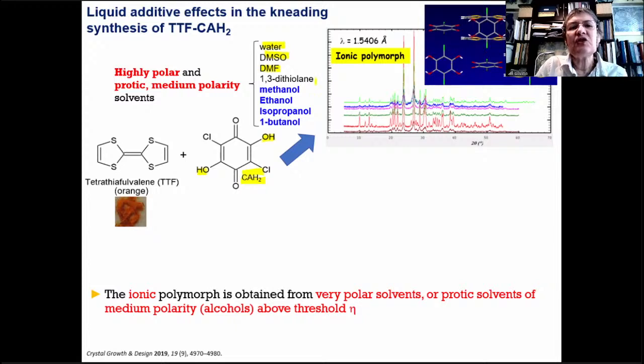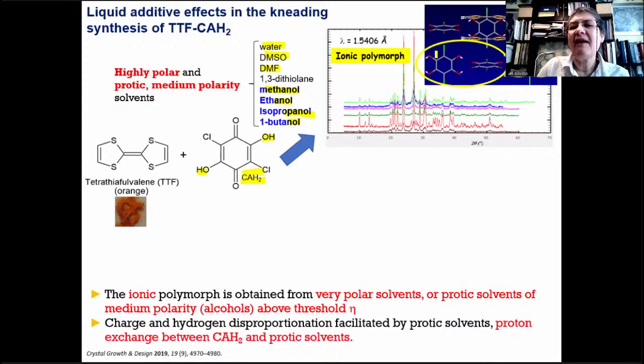And an interesting issue is that solvents of medium polarity, such as these alcohols, methanol, ethanol, isopropanol, and 1-butanol, also produce this ionic form. And these liquids always have to be used above certain threshold amounts to obtain single phases of this material. So in the ionic polymorph, we have a charge and hydrogen disproportionation occurring, in which between two chloranilic acid molecules, one of them has all the hydrogens, these 4 hydrogen atoms there, and the other one has all the charge, minus two, the charge of 2 electrons. And it also has these radical cation dimers.